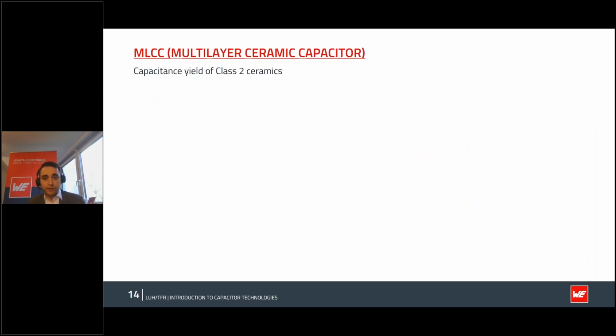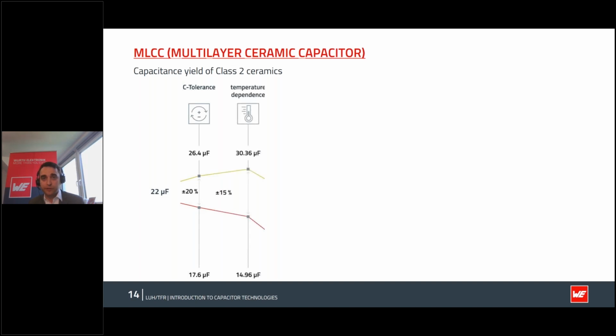Next, we have to look at all these effects combined. So for that, we'll pick a 22 microfarad capacitor. We'll pick an X5R ceramic to let you know. And usually X5R ceramics have a production tolerance of about 20%. So you might end up with 17.6 microfarad after that. Here we mostly focus on the worst case, as this is the defining factor for safe calculation. On top of this production tolerance, there is the previously mentioned temperature tolerance for X5R of 15% in addition to that. So you end up in the worst case with close to 15 microfarad.